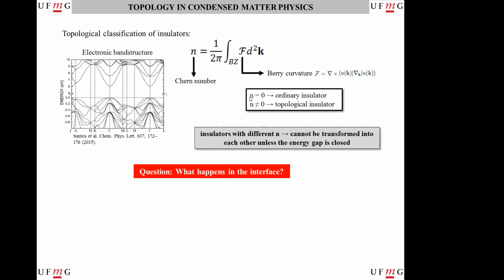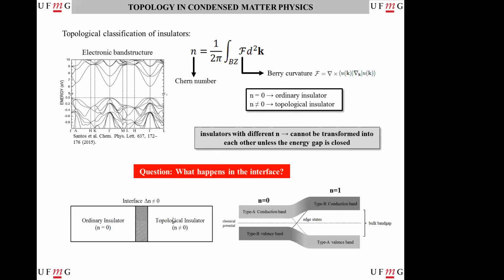So the question that remains is, what happens at the interface when we put two materials with different Chern number together? So when we put, for example, one with Chern number equal to 0 and another equal to 1, at the interface between them, since they have different Chern numbers, the gap should close. So just at the interface, some states will appear that make this connection. So at the interface, there are states in the gap, and outside of the interface, there are no energy states crossing the band gap.